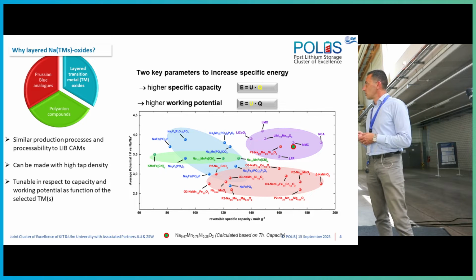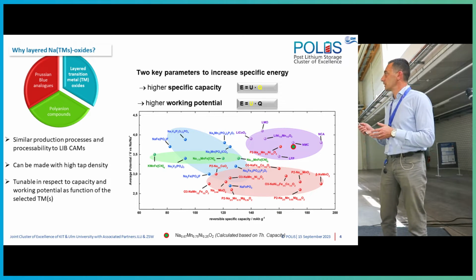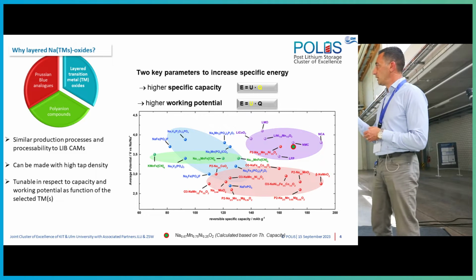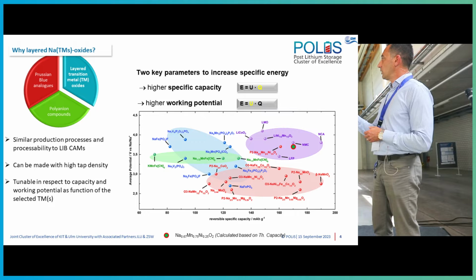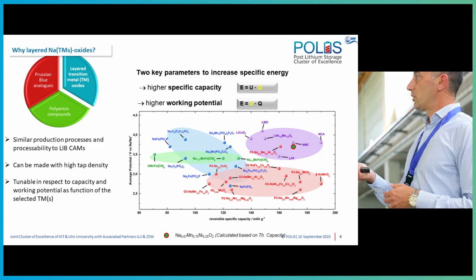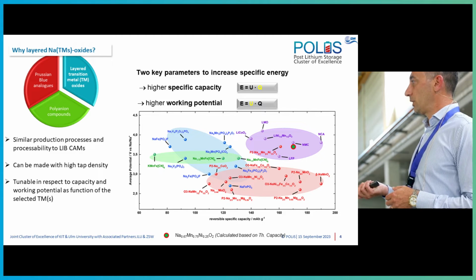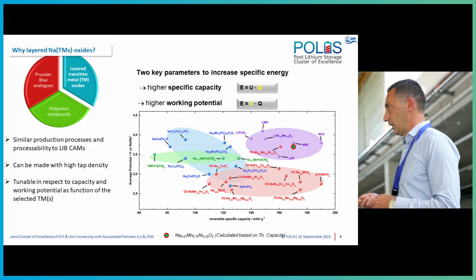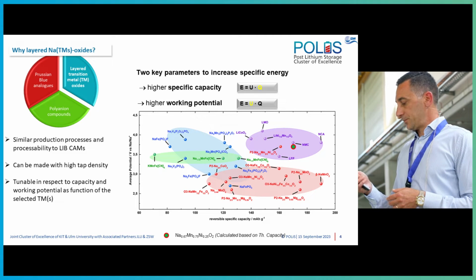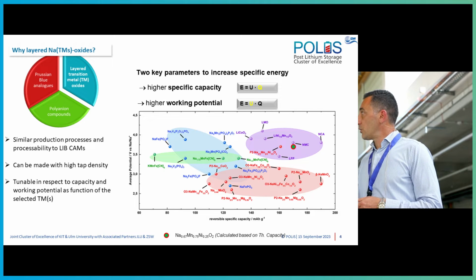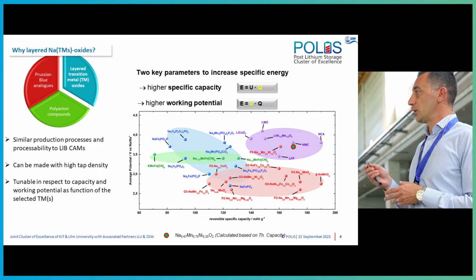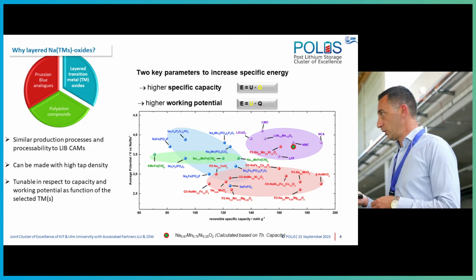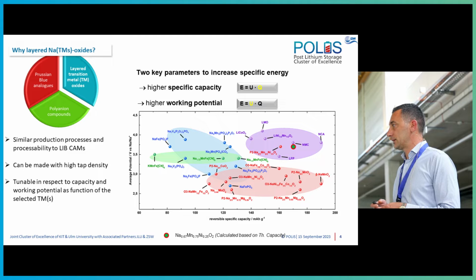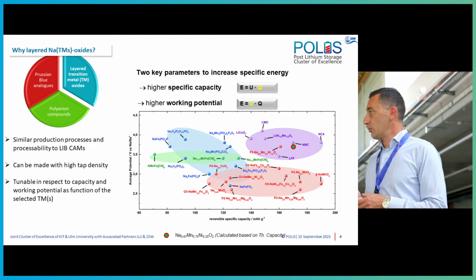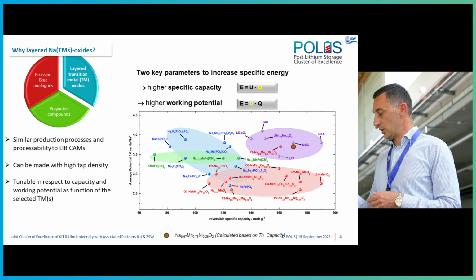Sorry, wrong button. So we tried to come up with this table, and what we want to do is basically to go in this direction: increase the average potential of the cathode material and increase the reversible specific capacity of the cathode. This is where our material is positioned. It is basically a sodium deficient manganese nickel layered oxide, manganese 3/4, nickel 1/4.